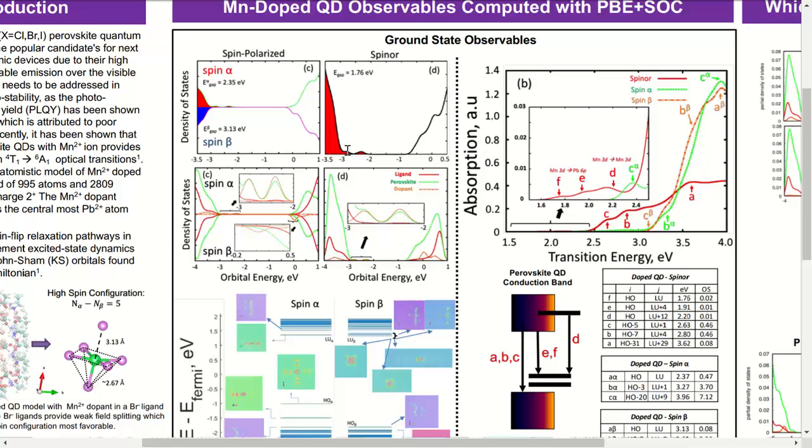And we do see that in the conduction band there are some valence D states hanging around just around the conduction band edge, which is a good sign because if you're trying to get photoluminescence for the materials, you want those D states to be near the band edge, so that after non-radiative relaxation, the electron occupies there.